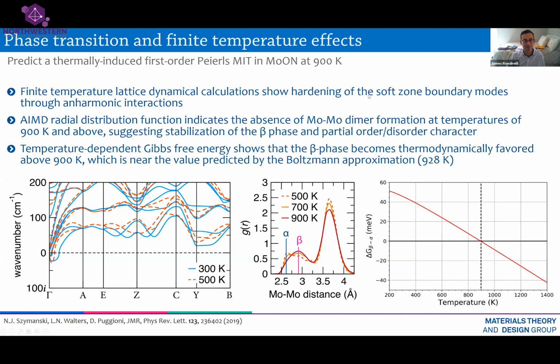It's awaiting experimental validation, but we're working with several groups, both those at Northwestern and elsewhere, to try to confirm this electrical phase transition. And just based on the temperature scales, we expect and do know from our detailed electronic structure study that the mechanism here is much closer to that, in fact, of niobium dioxide. Really, it's driven by this structure instability, whereas in vanadium dioxide, it's driven in part more from electron-electron correlation effects. And so this is the advantage of using first principles methods in the design of materials.